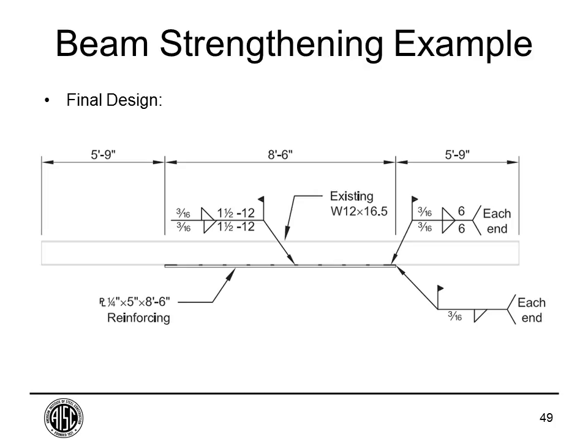So here's our final design. We have our existing beam. We have our 1/4 inch reinforcing plate, which extends over the 7.5 foot length between the theoretical cutoff points, plus an additional 6 inches on either side for the development welds. We have our 6-inch long 3/16 inch welds, plus an additional weld across the end of the plate, and our intermittent welds between the ends.